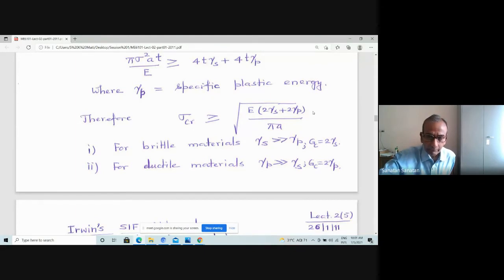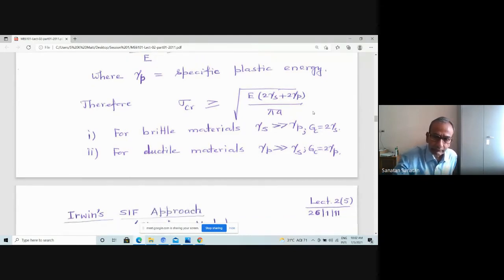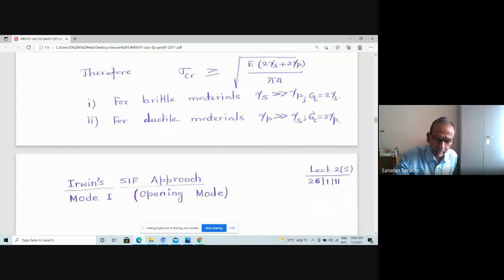And in fact, when it is a brittle material, then this gamma P, the plastic deformation energy, is very, very small, and surface energy is the stronger part of it, and therefore the earlier equation was valid for brittle material. But if it is ductile material, then gamma P is much higher than gamma S. So that's how this became the amended equation, and it did solve the problem, and it made it acceptable for people. So that's how it is.